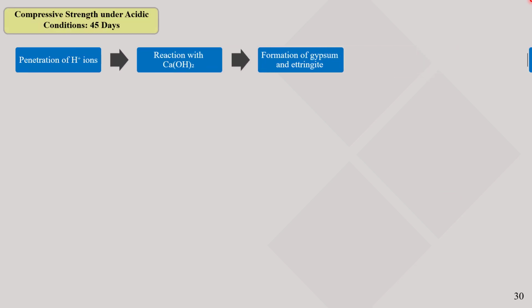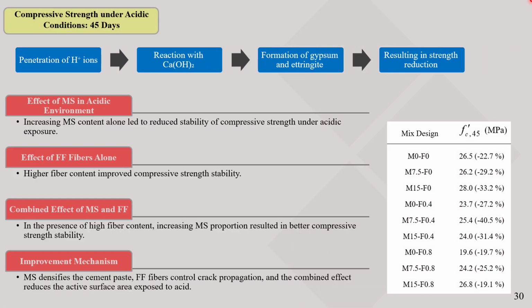Under the 45-day acidic condition, a degradation mechanism occurred. Hydrogen ions attacked the concrete and reacted with calcium hydroxide present in the mix, producing gypsum and ettringite. These secondary products are bulky and reduce the compressive strength. The results showed that higher microsilica content reduced strength stability, while higher fiber content improved compressive strength retention.